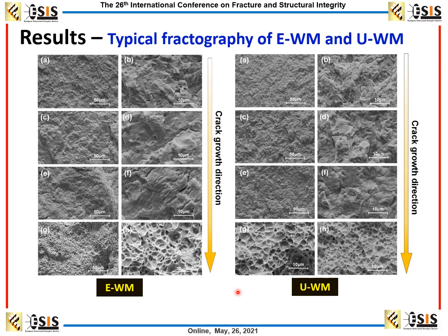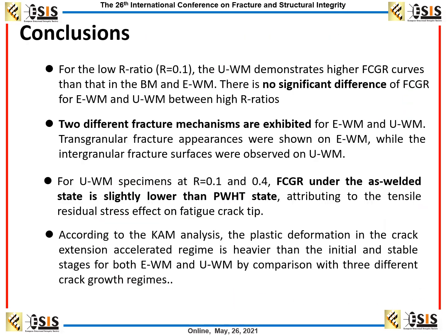Okay, so the last section. The conclusion contains four points. The first one is that for the low R ratio, the undermatched weldment demonstrates higher FCGR curves than the base metal or even matched weldment. There is no significant difference between FCGR for even matched and undermatched weldment at high R ratio.